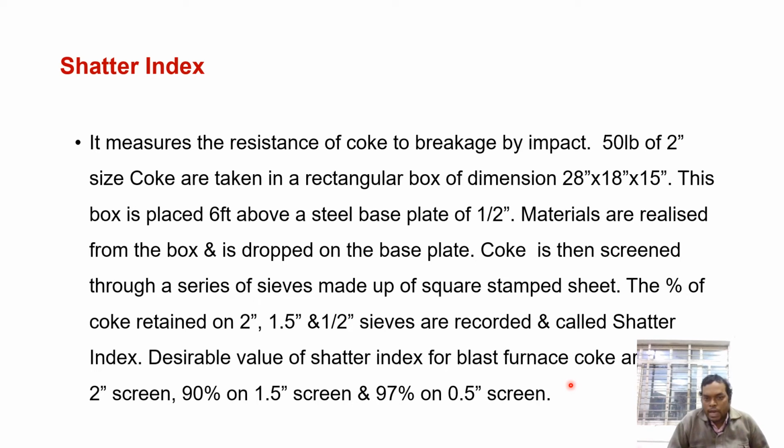The desirable value of shatter index for blast furnace coke is 2-inch screen, 90% on 1.5 inch screen and 97% on 0.5 inch screen.